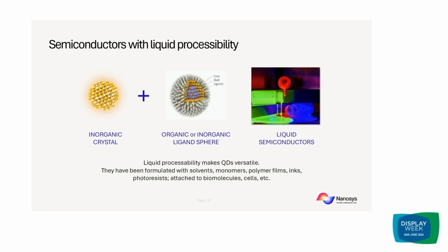So some of the benefits of what is on the outside of these ligands are what was described in the first half of this talk about passivating surface states, increasing your quantum yield. But the other half of the system is the flexibility of what you can do with those ligands on the surface. So you can imagine 2 different control points. You have control over the type of chemical bonding that you have from the ligand to the inorganic portion. And you also have complete control over the main component of that ligand molecule itself.